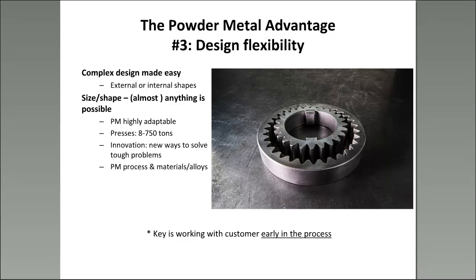In powder metal, the uniformity of the teeth is determined by the die and tool members. And these are very tightly controlled tolerances, usually in the 1/10,000th of an inch tolerance range, that are used to press components. Further, if you look at the inner diameter of the inner gear, that has two lugs on it, which are actually something that would, in standard wrought material, perhaps be created by broaching or another more expensive process. So this is something that's inherent in powder metal. A gear is a good example, albeit an older one, of where powder metal finds its best suited applications. Now, that gear, by the way, could be a Class 6, Class 8 AGMA scale gear.